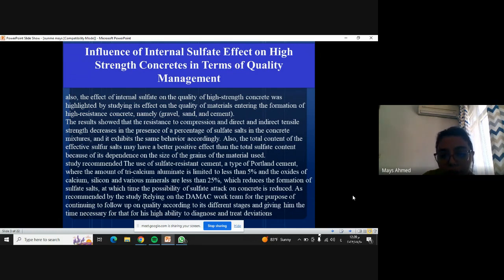Also, the total content of the effect of sulfate salt may have a better positive effect than the total sulfate content because it depends on the size of grains of the material used. I mean, gravel, sand, and cement. A study recommended the use of sulfate resistant cement, a type of Portland cement, where the amount of tricalcium aluminate is limited to less than 5% and the oxides of calcium, silicon, and various minerals less than 25%, which reduces the formation of sulfate salt, at which time the possibility of sulfate attack on concrete is